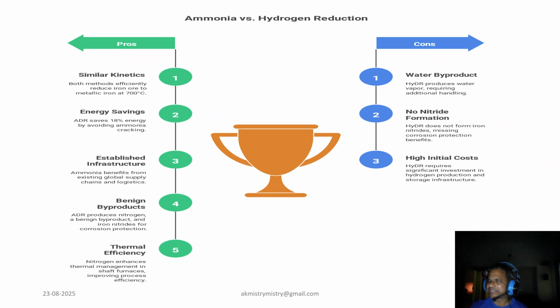However, hydrogen-based direct reduction, that is HYDR, has some cons also, like a water byproduct. HYDR produces water vapor which requires additional handling. No nitride formation: HYDR doesn't form iron nitrides, meaning it misses out on the corrosion protection benefit that nitrides offer. High initial cost: HYDR requires significant investment in hydrogen production and specialized storage infrastructure, leading to higher upfront expenses.